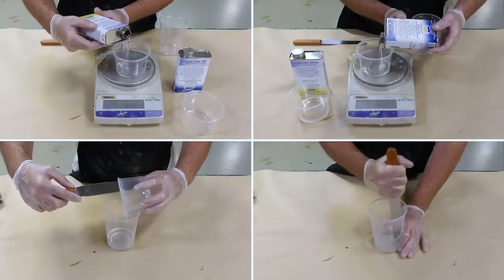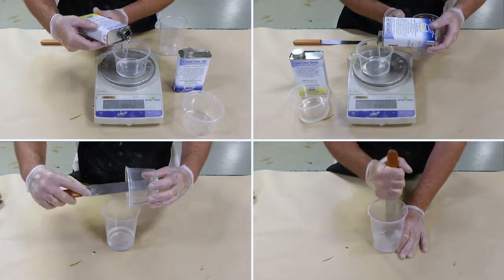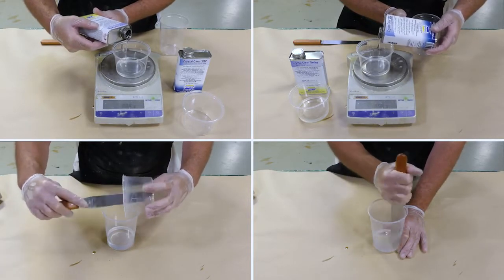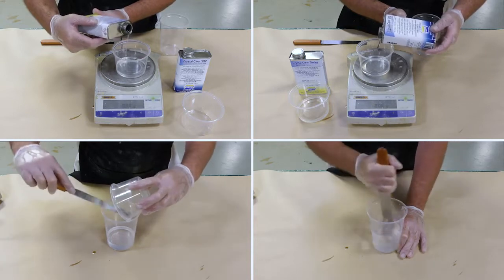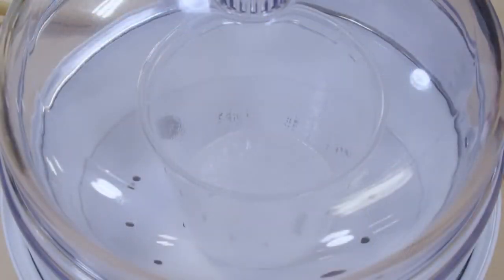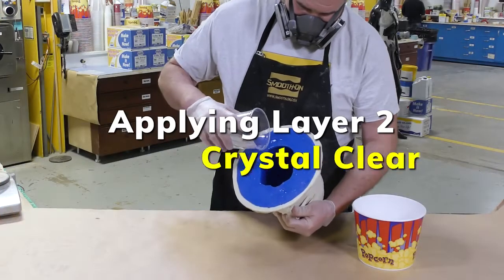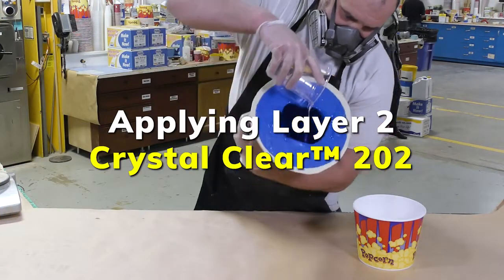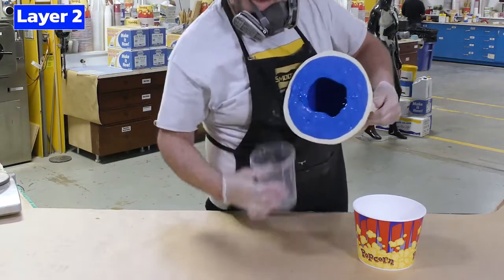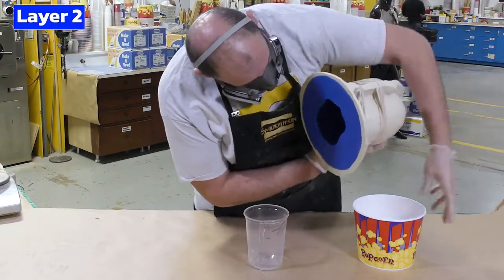To dispense our second layer of material, we're going to follow the same dispensing instructions as we did previously. Just like we did on the first layer, to minimize the air bubble entrapment in the material, we're going to vacuum degas the material before pouring it into the mold. Just like in the previous layer, we're going to spin the mold in a 360 degree way to make sure that all the surfaces on the inside are coated with a layer of material.